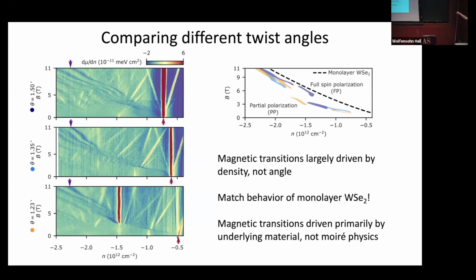And interestingly enough, this dashed line is what you get for magnetic transitions just in monolayer tungsten diselenide. No moire, no second layer, nothing like that. Actually, if you have AB Bernal naturally occurring bilayer untwisted, it also is very similar to this transition. And I think the takeaway message is these are very, very close to where the magnetic transition occurs in monolayer tungsten diselenide.